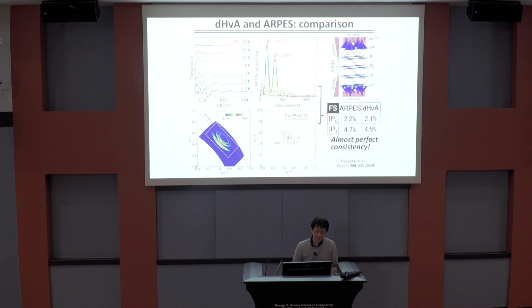Of course, ARPES is very sensitive to surface state, so we confirmed this pocket is really coming from the bulk state. We studied quantum oscillation as plotted here, and Fourier transform peaks are consistent with the double small Fermi pocket. The size of each pocket is listed in this table, and the percentage of the Brillouin zone matches well between the quantum oscillation and ARPES results.